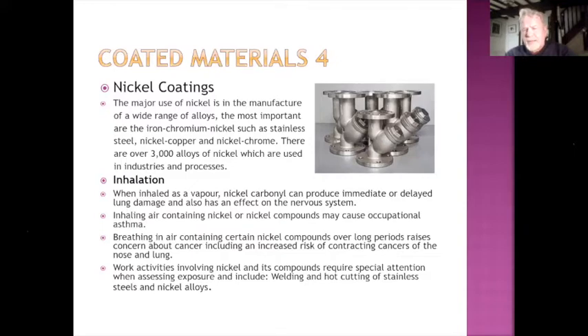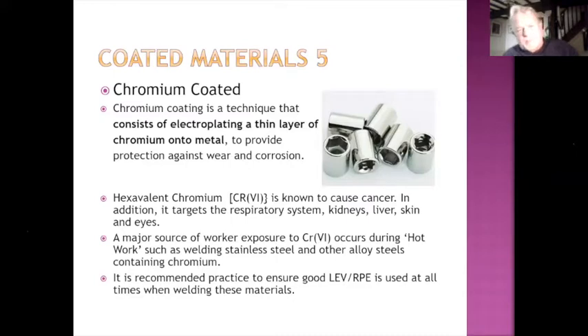And finally, any activities which require special attention when assessing exposure: welding and hot cutting of stainless steels. So if you use a plasma cutting process on stainless steels, again, there's a considerable amount of fume that comes off that process, so be very wary. Chromium coating, in many respects, is for the aesthetic look of the product, and also to give it excellent corrosion resistance. But again, we've got the hexavalent chromium, and with any hot work there's a potential for that hexavalent chromium to be released. Therefore, it's recommended practice to ensure that you have good local extraction, ventilation, and respiratory equipment as well.